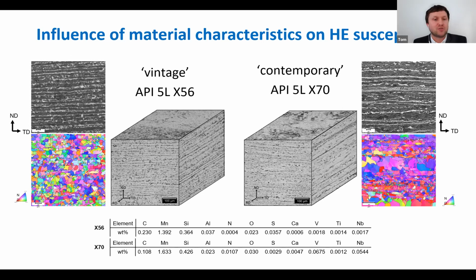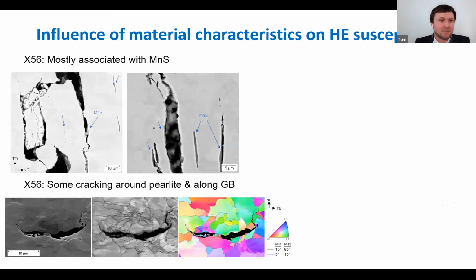So they show different trapping characteristics, different diffusion characteristics, and they lead to a different sensitivity to hydrogen embrittlement. In the case of, for instance, charging very severely, which is happening in cathodic overprotection, you can see that in the X56 material, a lot of cracking is present. Most of the cracks are hydrogen-induced cracks, because this is without mechanical load.